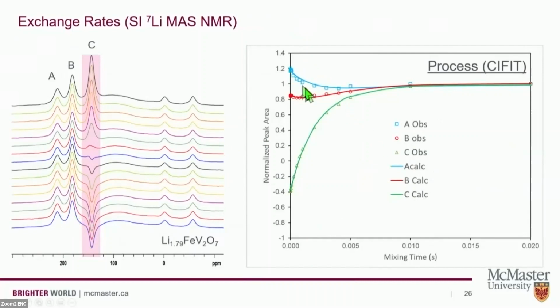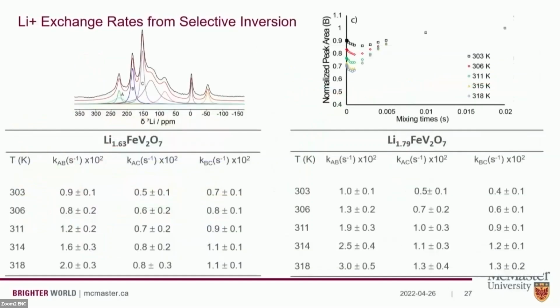And what we look for is this signature transient well that's indicative of chemical exchange, or a loss of intensity from the A peak or B peak before it relaxes back to equilibrium as we go through this series of spectra. And we can do this whole data set in one evening, whereas we used to be getting 1 EXSY experiment per 1 evening. So this is a nice efficient process. And we fit this data using a program written by my colleague, Alec Bain, who passed away a few years ago, but we still know and love all of his work.